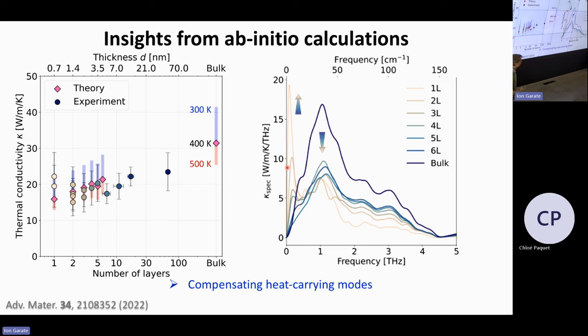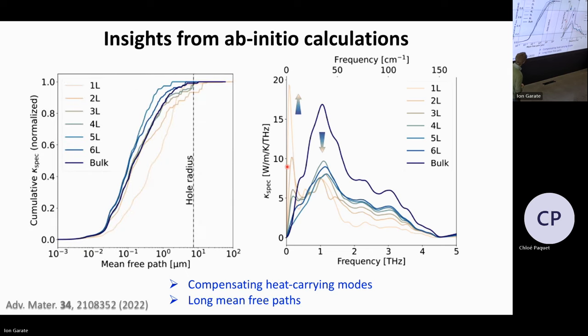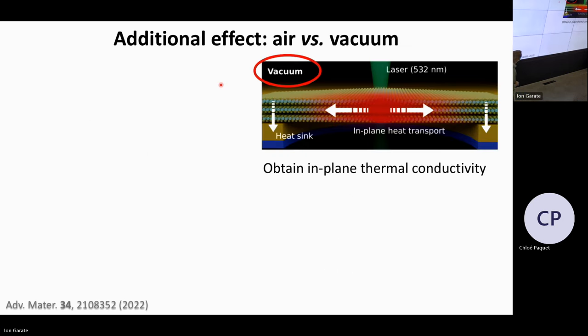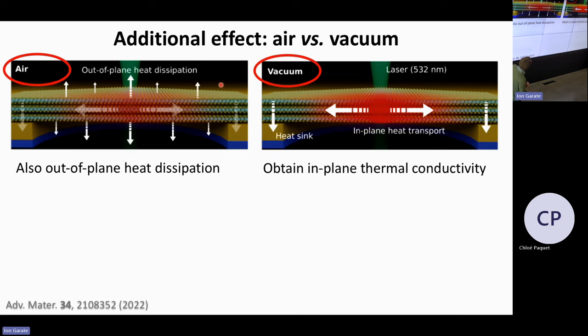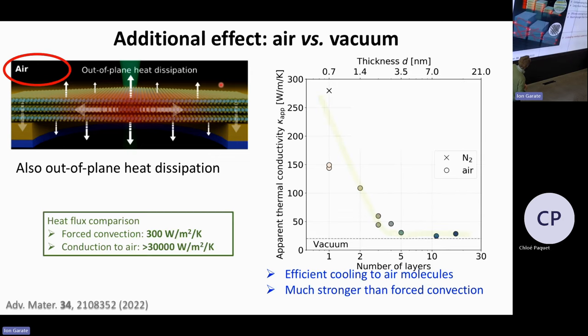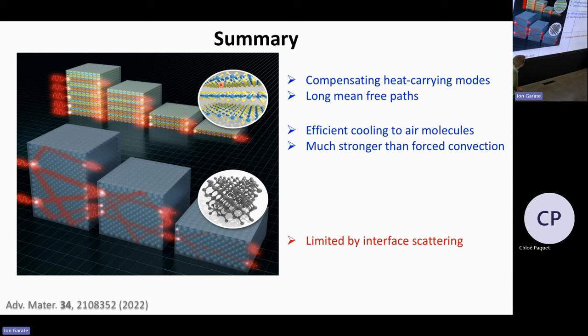So one part of the answer is you have compensating heat carrying modes when you start thinning down. And they can be quite long lived, even more than 10 micron of mean free path, some of these low energy modes, which also highlights the importance of having such large suspended structures. Now, okay, this is an additional effect. You can get some cooling to air, which is maybe not so interesting.